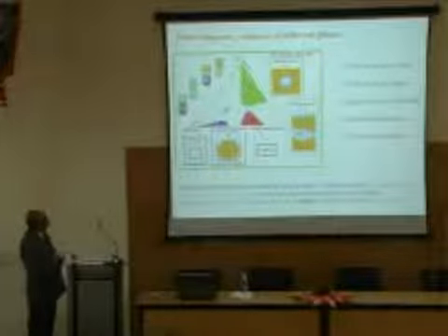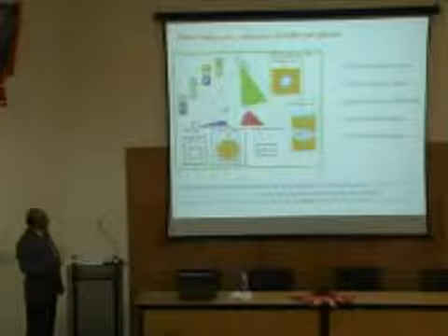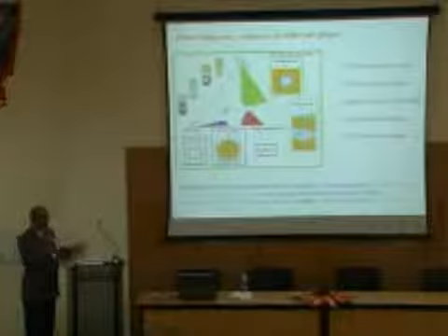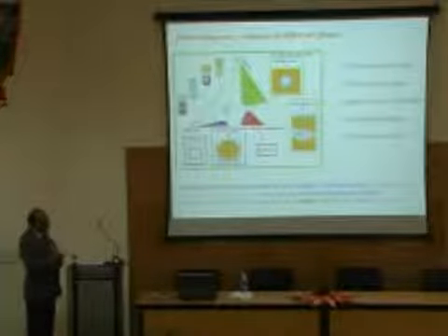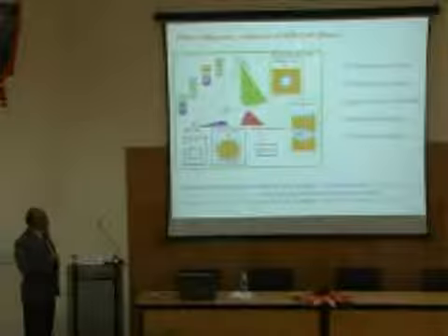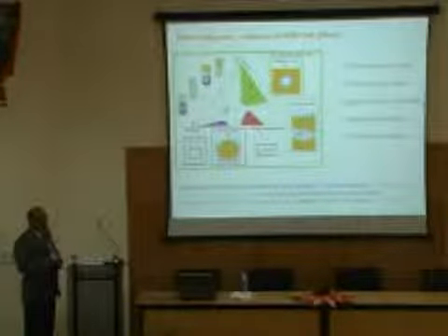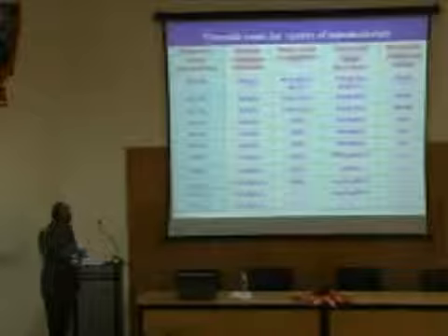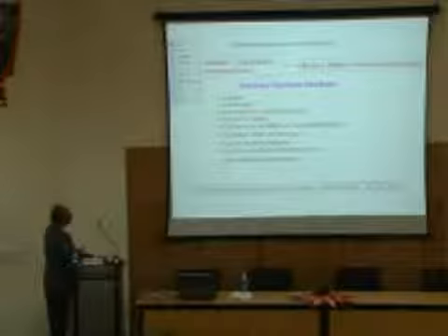And you have to know that you have several parameters now. Oil is there, surfactant is there, water is there. Sometimes we have a fourth parameter which is called a co-surfactant, and you must know when you have to plot what is called a phase diagram. That means if I take X amount of this or Y amount of this or Z amount of this, what will I get? So, by knowing the phase diagram, you know what kind of structure you will get. Okay? So, you can get a micelle or a reverse micelle or a bicontinuous medium, etc. So these are all design. So these are some materials, nanoparticles we make. Okay, I missed that.